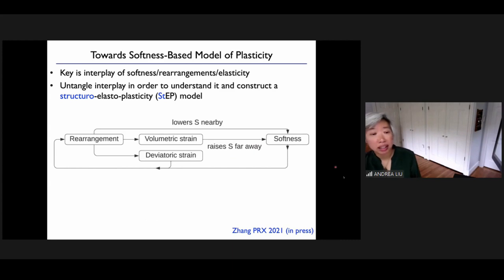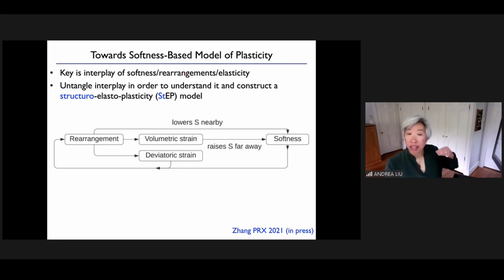And so what we are doing is to use this quantity, softness, as a tool to characterize structure, to look then at the interplay of softness with dynamics, the rearrangement, with elasticity. The interplay of rearrangements and elasticity is what has been embedded in elastoplasticity models. Rearrangements give rise to some strain far away, or elsewhere. That strain can trigger another rearrangement if that strain exceeds the yield strain locally. And so that interplay of strain and rearrangements gives you avalanches, for example, or gives you the evolution of the system under strain.